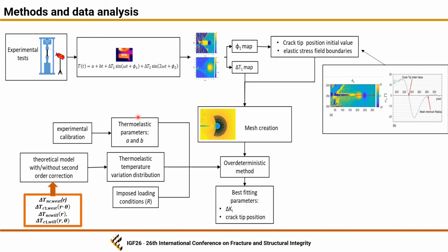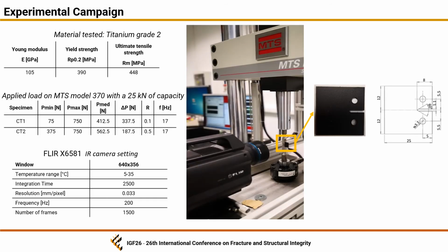In particular, an over-deterministic set of equations is written according to the material constant, the corrected and non-corrected thermoelastic temperature variation, with and without mean stress effect, according to Williams and according to Westergaard, and imposing the loading condition. The over-deterministic method leads to the best fitting parameters, that are the stress intensity factor for Westergaard and the three coefficients considered, the stress intensity factor, T stress, and constant A for Williams, and it also leads to the crack tip position.